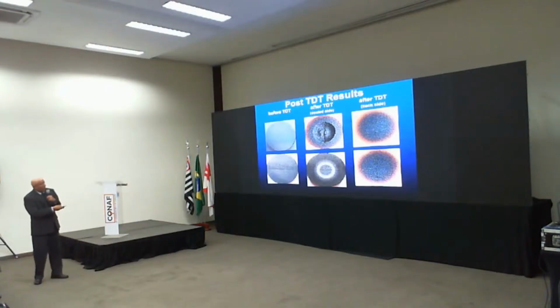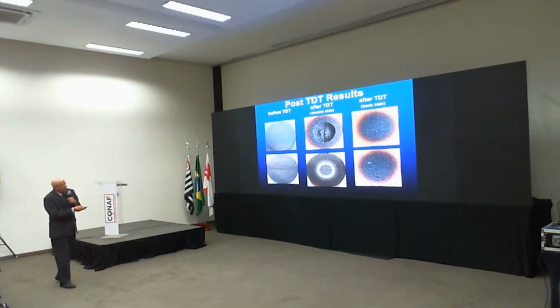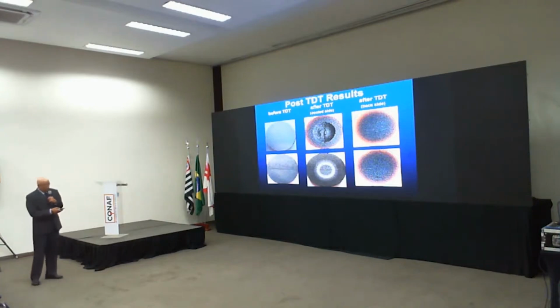This is with the coating. This is a micrographite coating. This is the heat affected zone. There is a fine crack. But on the back side, you can see that that particular coating is protecting against that loss of sand relative to that situation. The video here, please.